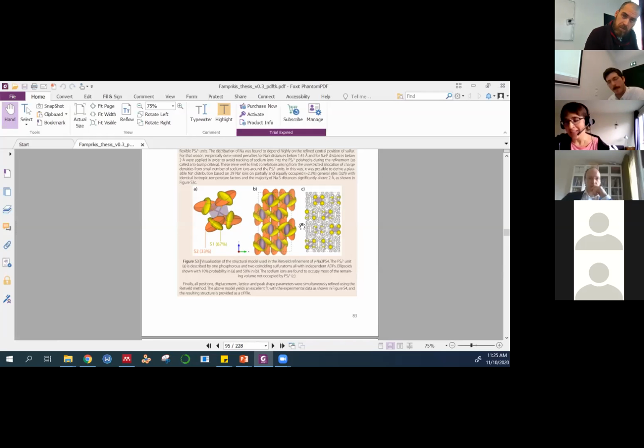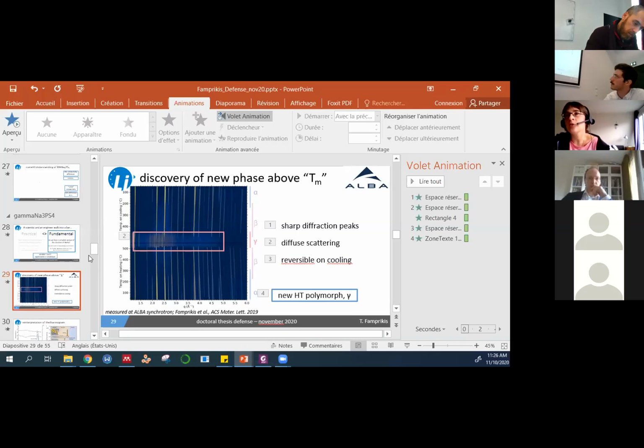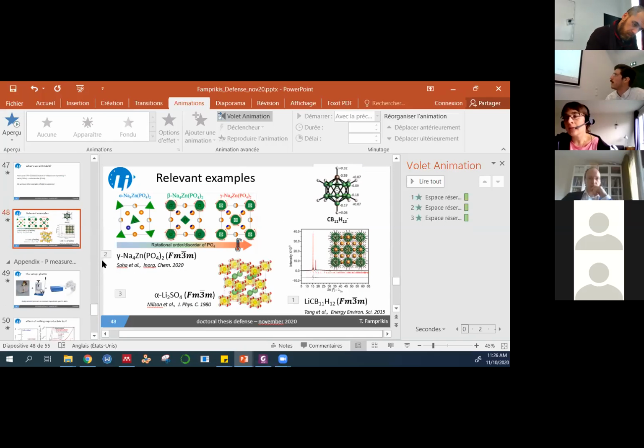Going back to this, I think the main point is why is the symmetry so low at high temperature? Naively, we would expect, as seen in so many phases, and this is Curie's principle and so on, that when you increase temperature or disorder, you go to higher symmetry. If you have some rotating PS4 or sodium moving everywhere, you expect to end up with a small cubic cell, as was reported in so many compounds. So here I have two things that are strange. FDDD is pretty low in symmetry, and the unit cell is pretty large, with one lattice parameter of 20 angstrom. I can see that it indexes perfectly, but with rotational disorder of the PS4 that you show, crystallographically you do not observe this at all. So this is really surprising for me.